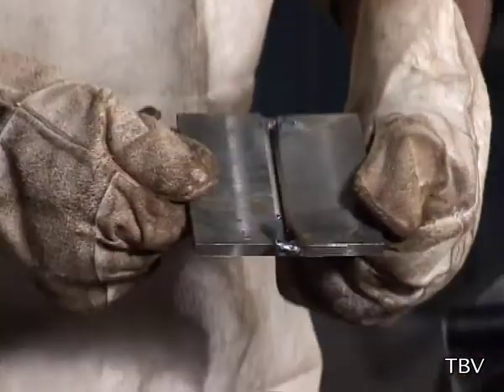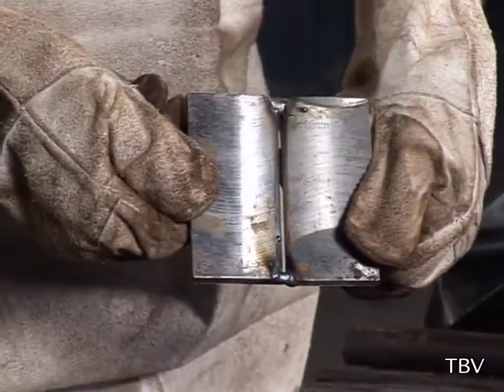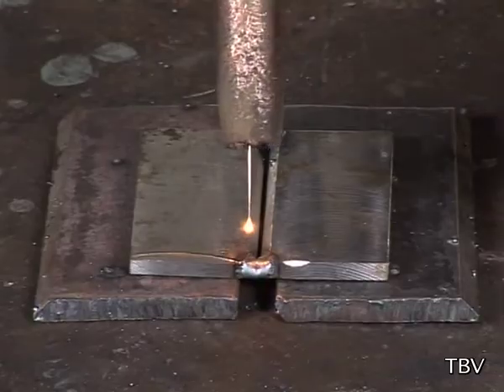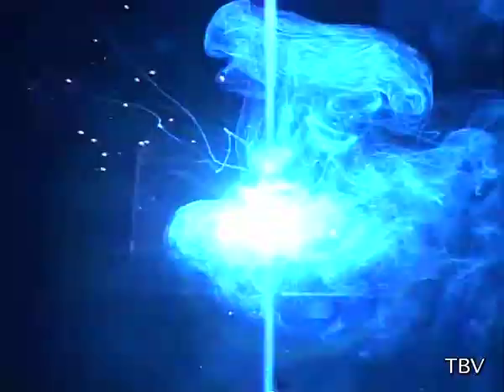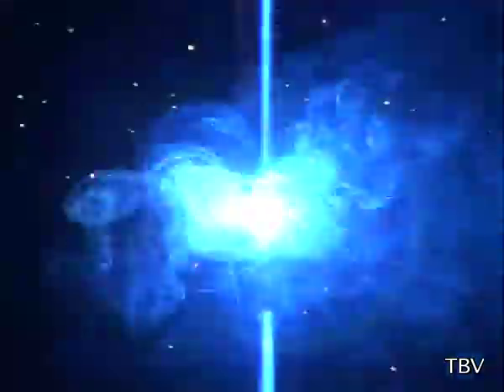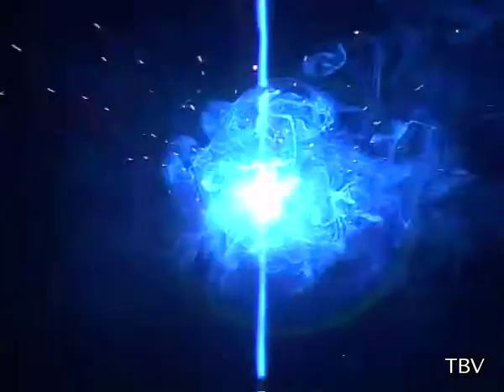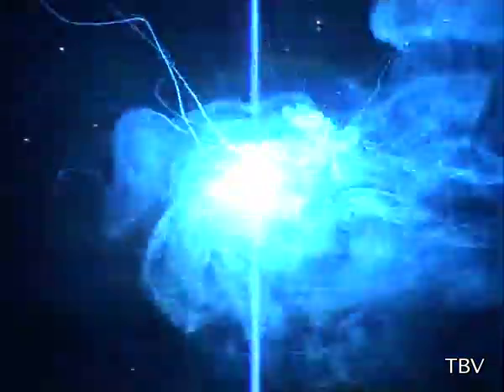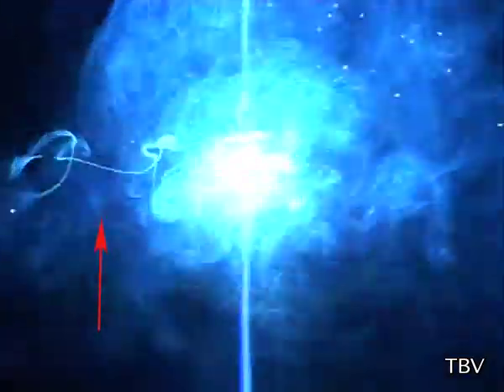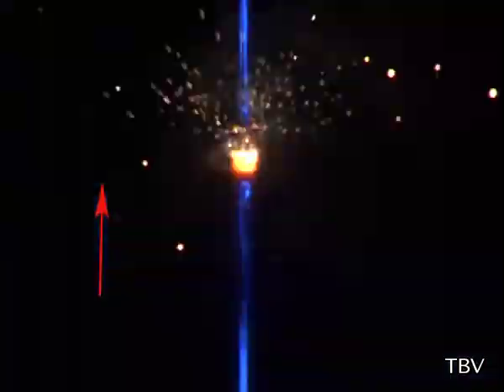Open the CO2 gas flow in the gun before striking the arc. Strike the arc, maintain a filler wire stick out at 8 to 10 mm from the end of the contact tip as required for dip transfer mode. Maintain the angle of the torch at 10 to 15 degrees towards the direction of travel. The first deposit of the bead is called the root run.